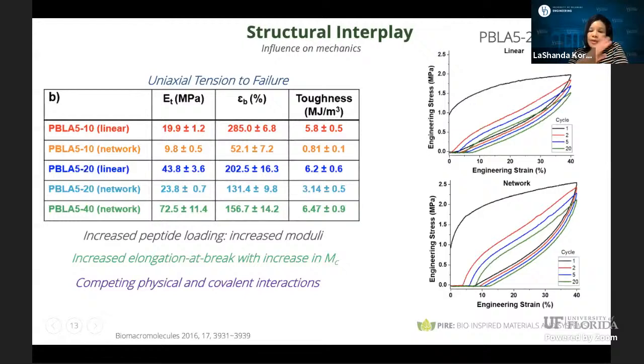And so a couple of key points here. I won't go through everything, but as we increase peptide loading for both the linear and the network systems, you actually see that the modulus increases, as we would anticipate, much like when we showed in the first generation systems. For our network systems, you not only get an increase in moduli, but you also get an increase in the elongation at break, which is not typically what happens in these systems. You have one at the sacrifice of another. And the reason why we're able to achieve this increase in the elongation at break is because we're increasing the molecular weight between crosslinks, because we're adding in more of the peptide to modulate the composition.